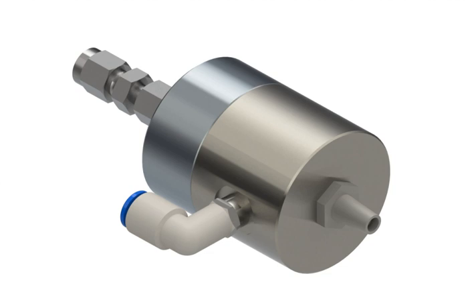Research has shown that ultrasonic nozzles can be effectively used to manufacture proton-exchange membrane fuel cells. The inks typically used are a platinum-carbon suspension, wherein the platinum acts as a catalyst inside the cell. Traditional methods to apply the catalyst to the proton-exchange membrane typically involve screen printing or doctor blades. However, this method can have undesirable cell performance due to the tendency of the catalyst to form agglomerations, resulting in non-uniform gas flow in the cell and prohibiting the catalyst from being fully exposed, running the risk that the solvent or carrier liquid may be absorbed into the membrane, both of which impede proton-exchange efficiency.